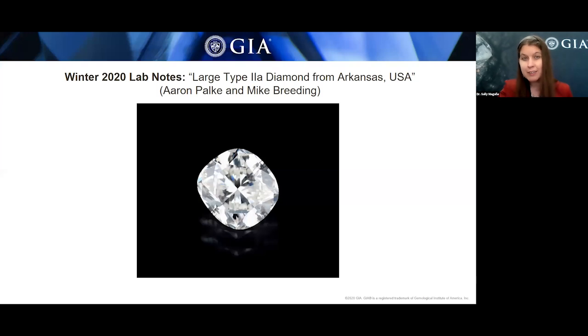Surprisingly, IR spectroscopy revealed that this stone is a type 2A diamond with no measurable nitrogen impurities. Now, we've known that only about 1% to 2% of colorless to near colorless diamonds are type 2A. So definitely discovering a type 2A gem diamond is rare enough, but for those of us who live in the United States, uncovering one from here where few diamonds occur was quite interesting indeed.